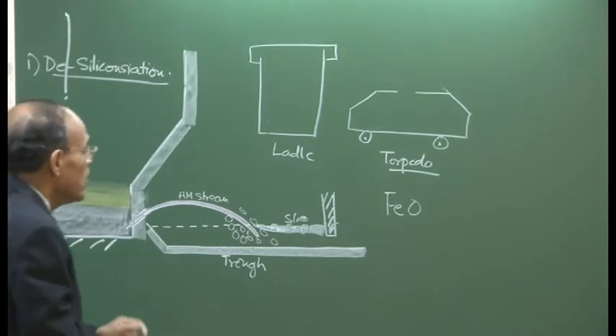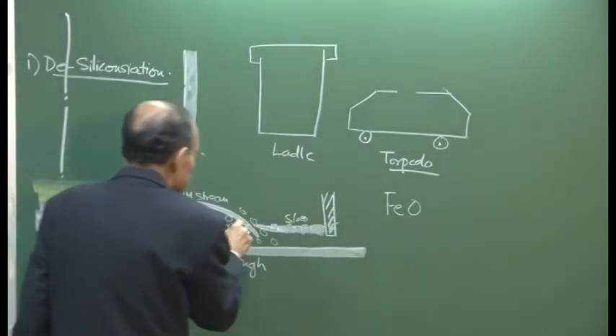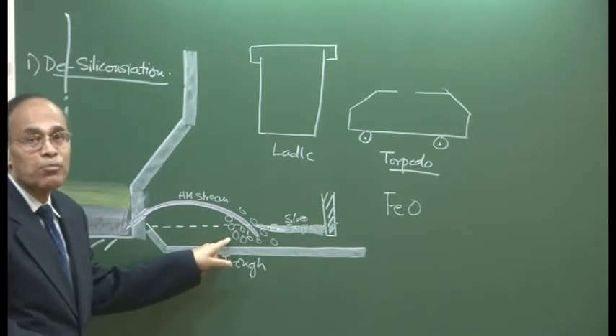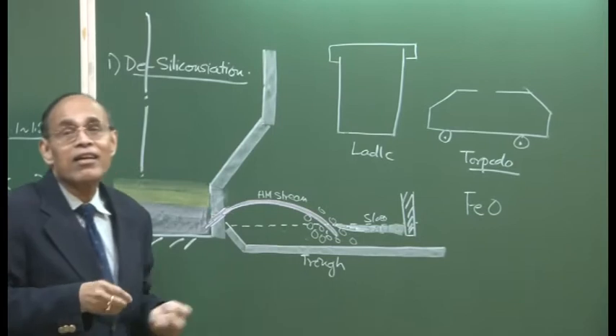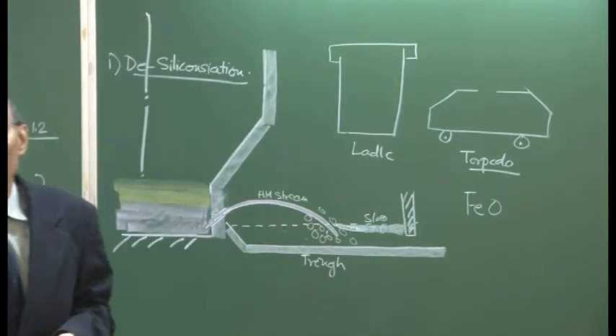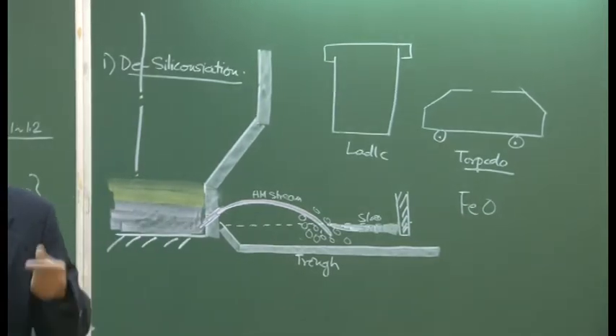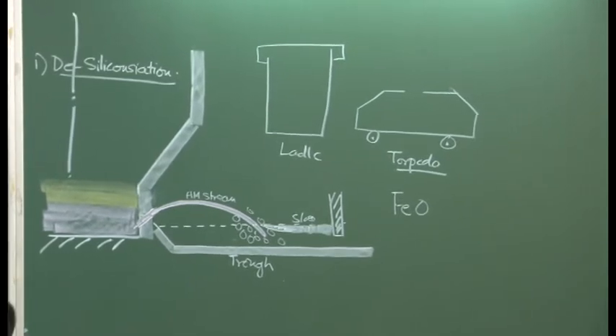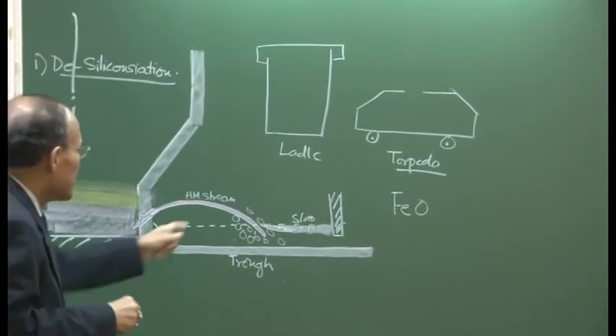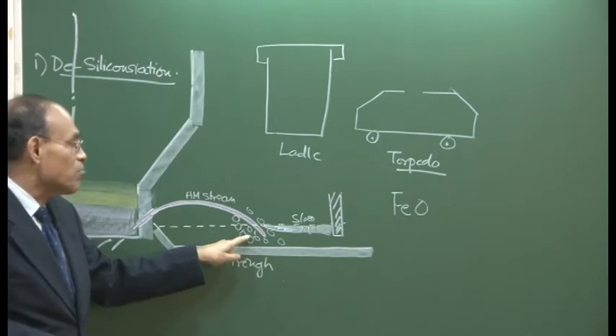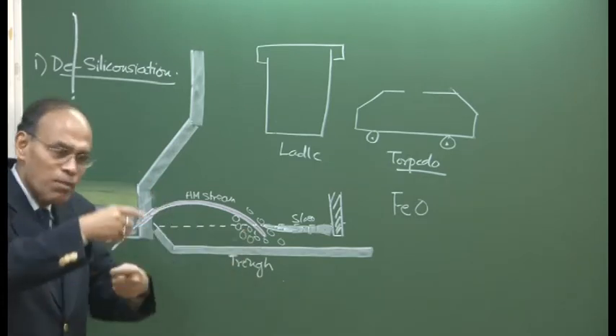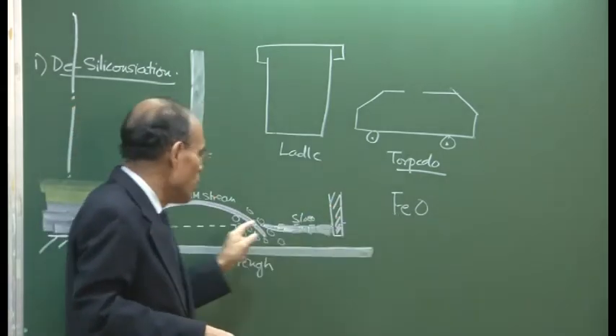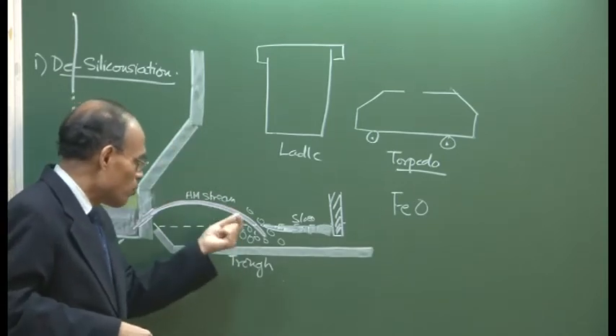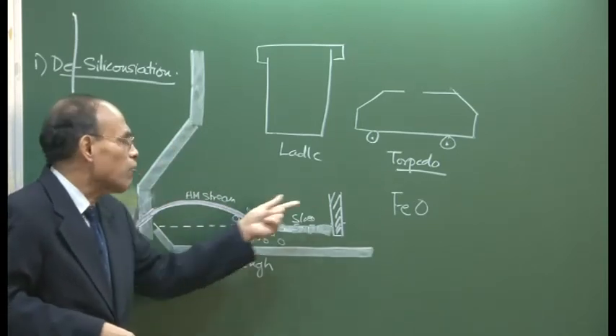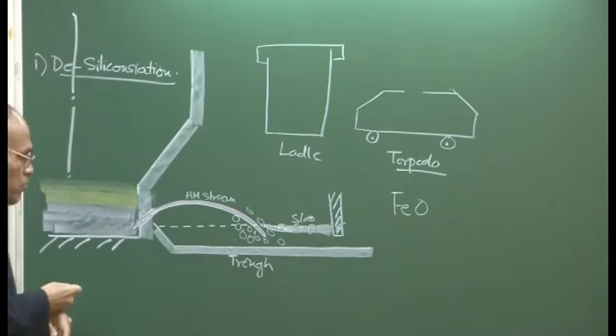And this mill scale can be added to the flowing hot metal itself, and there is a huge amount of churning motion here. It is like water flowing in a bucket when you open the tap, and you observe how vigorously the water contained in the bucket is stirred. It is the same kind of scenario which is taking place here. So the melt is extensively stirred, and if you put powders of FeO or small little pieces of FeO here, that FeO tends to get immediately mixed.